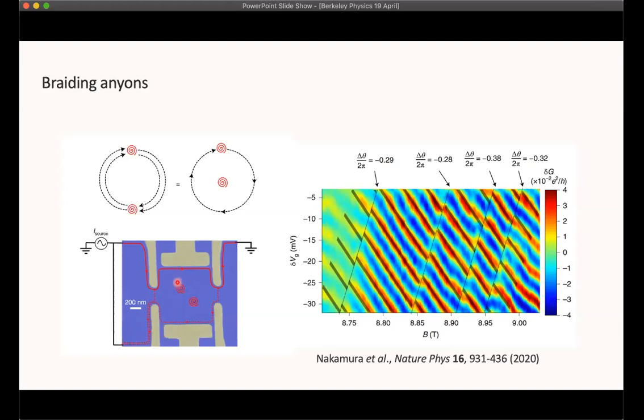Now, some localized defects or disordered potentials inside this region can mean that particles become trapped and localized inside this region of the interferometer. So interestingly, what they then did was they varied the applied magnetic field and they changed some local electric fields using a gate voltage. And they see these large interference effects, these oscillations from red to blue in the conductance.